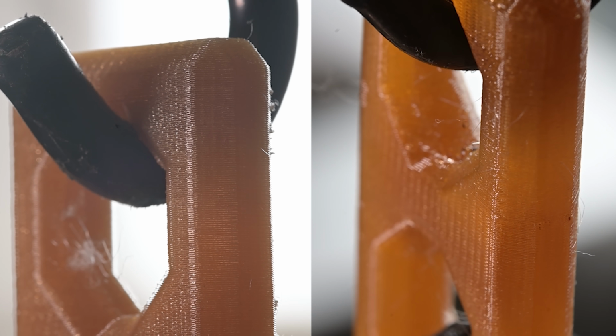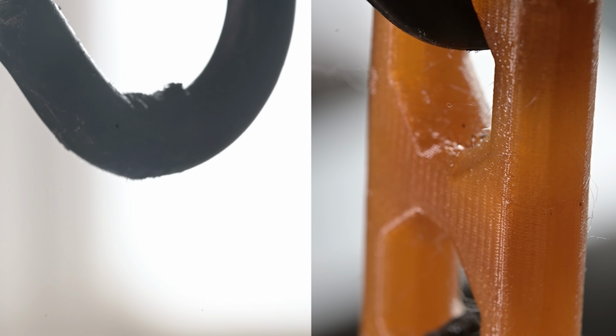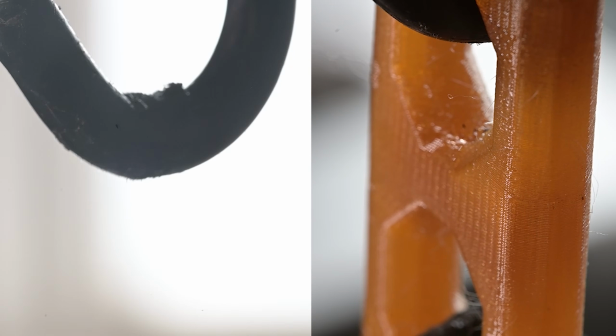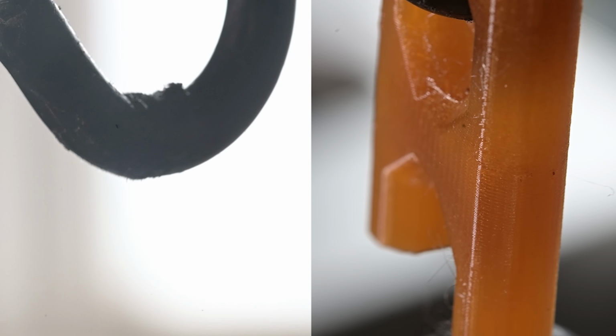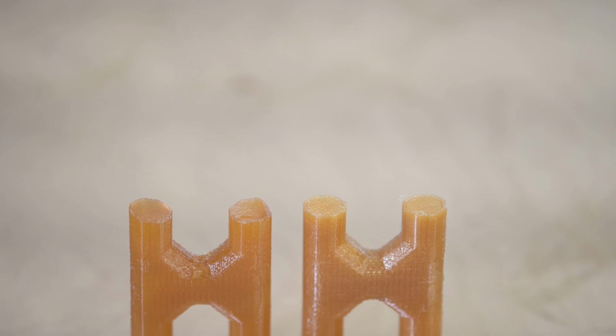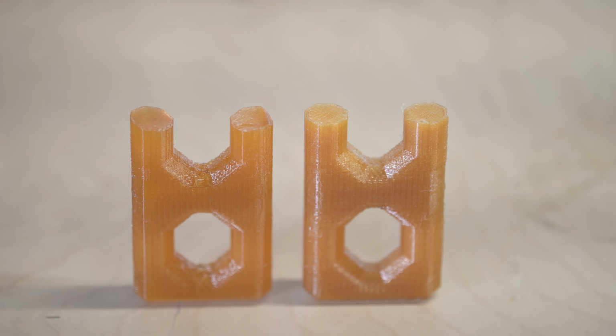So, how can chamber temperature alone reduce strength by this much? And why did annealing recover so little of it? The answer lies in the thermal history of the print. Interlayer welding depends on polymer chains remaining mobile long enough to diffuse across the boundary between layers.